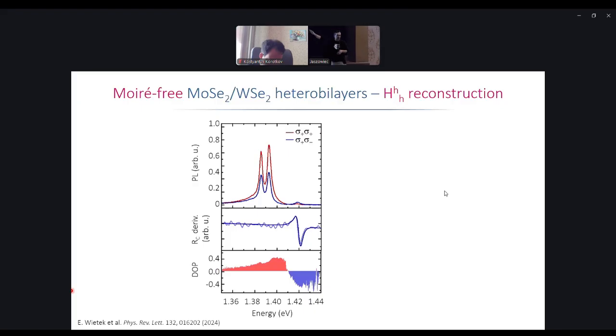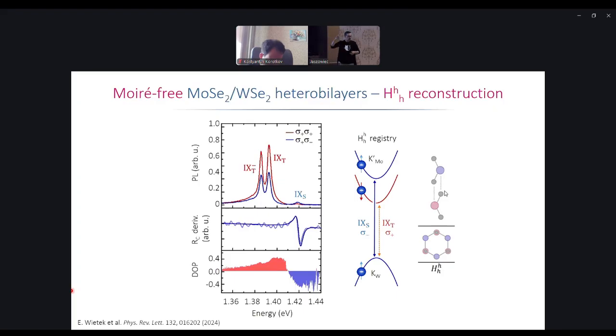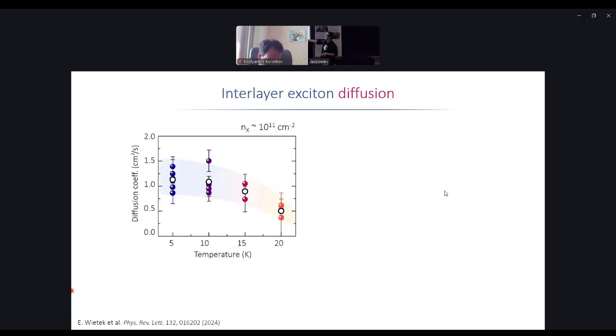This slide I will skip. This is for people who are working with heterostructures, to convince you that this is a specific registry where you can look at polarization, at g-factors, at energy positions. This is at this point well understood. And then we go to transport and we see again something semi-classical. The diffusivity is high. The numbers are 100 to 1,000 times higher than you will have in Moiré. And as the temperature is increased, the transport is either constant or starts to decrease.